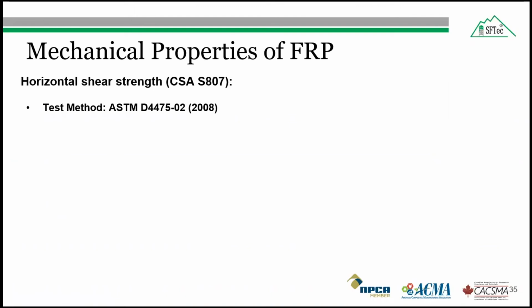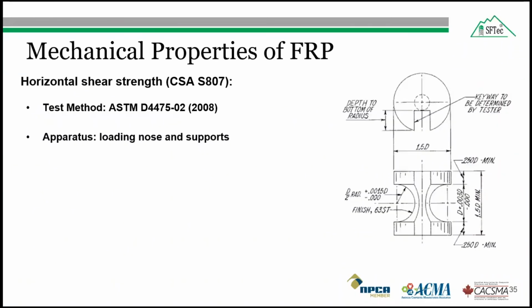So the next mechanical property is the horizontal shear strength of the FRP specimen, which was tested according to ASTM D4475. And this test is only required by CSA S807 for qualification tests. So if you are following CSA S807 for the qualification test, then you have to do this test. The test apparatus consists of a loading nose and supports. The loading nose was a suitable steel rod with a groove in the diameter of the rod machined in its lower end, like here you can see it. And the bottom support was adjustable to allow for testing at various span to diameter ratios.